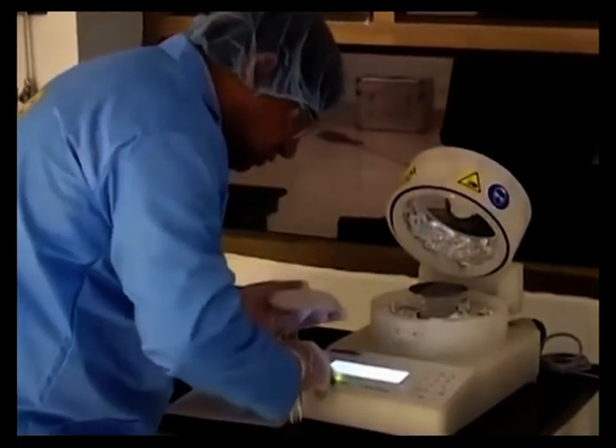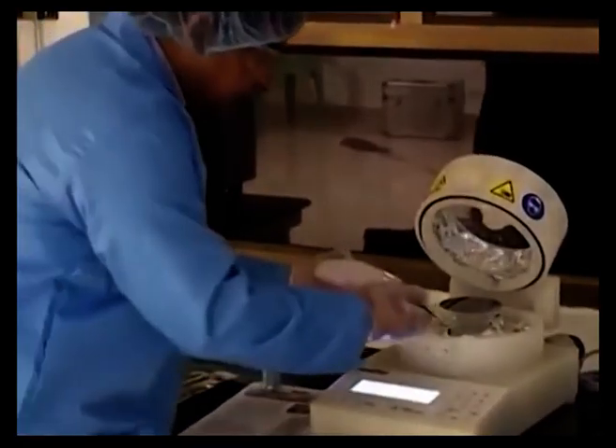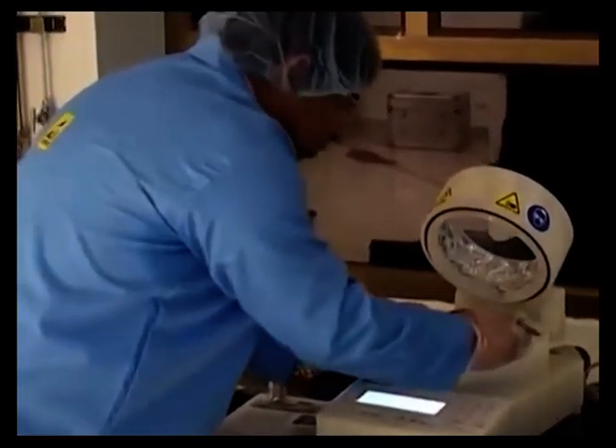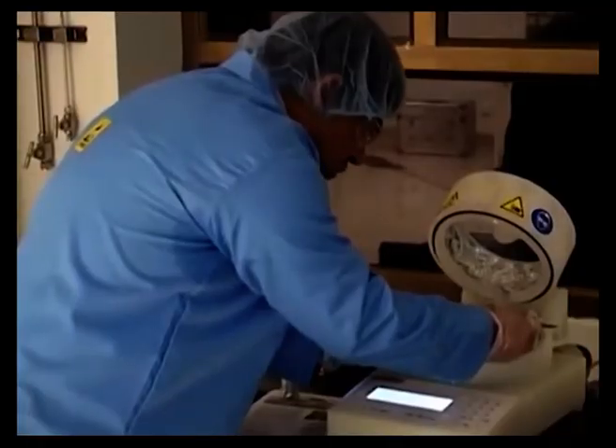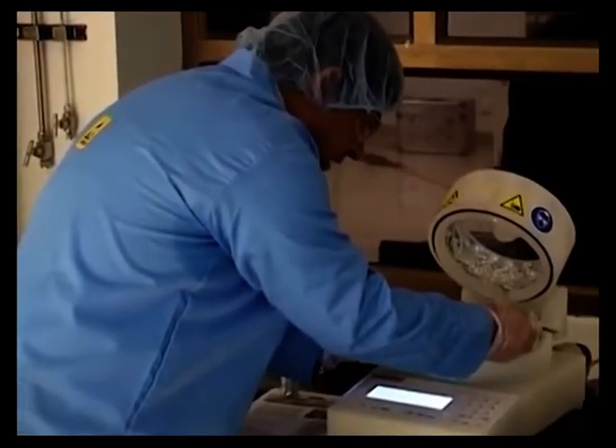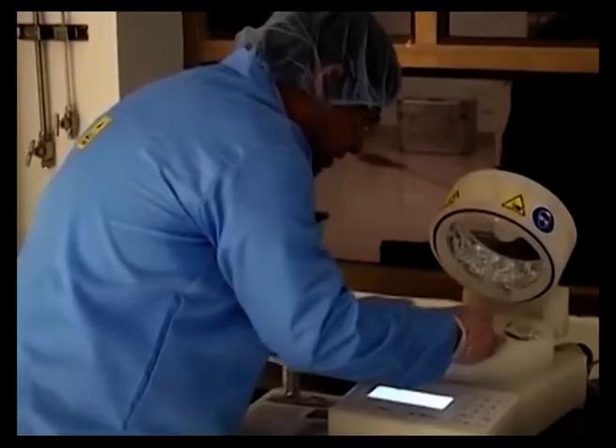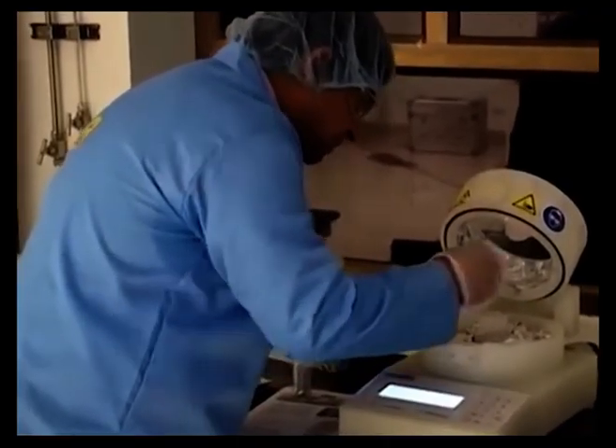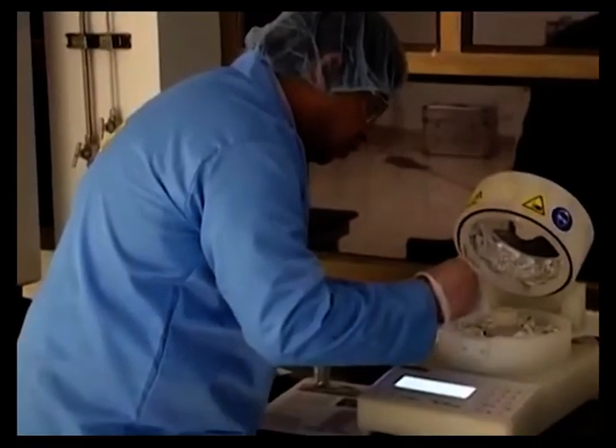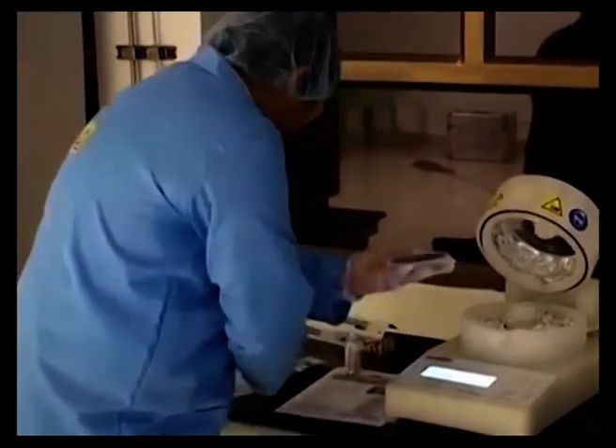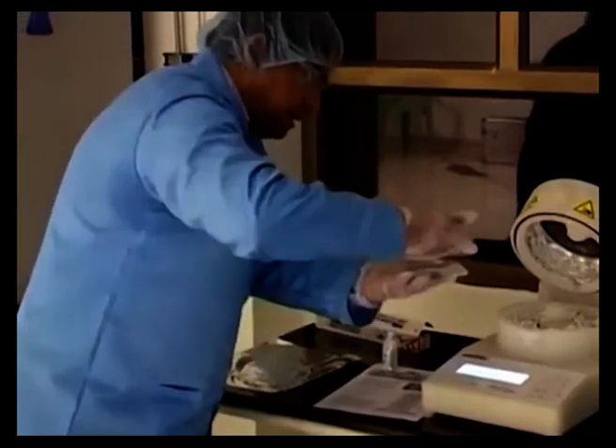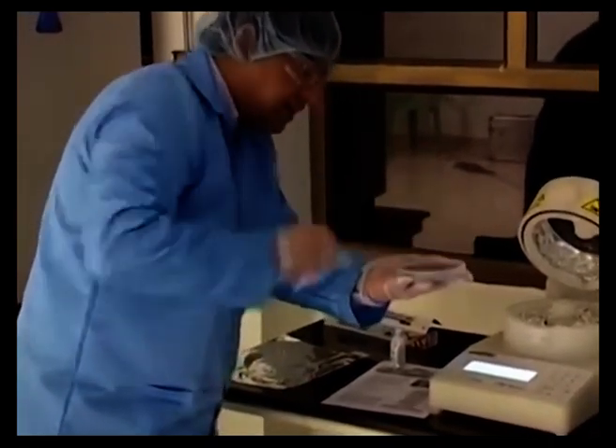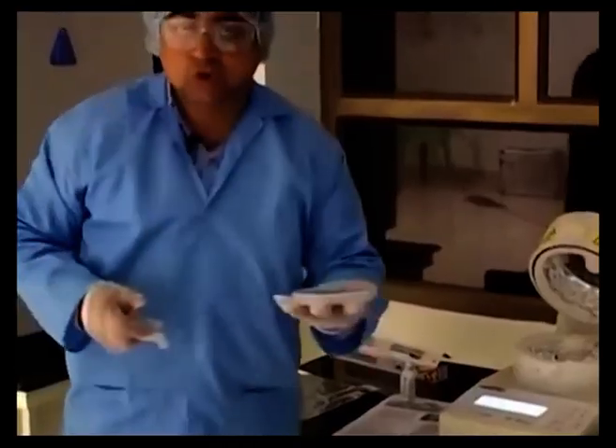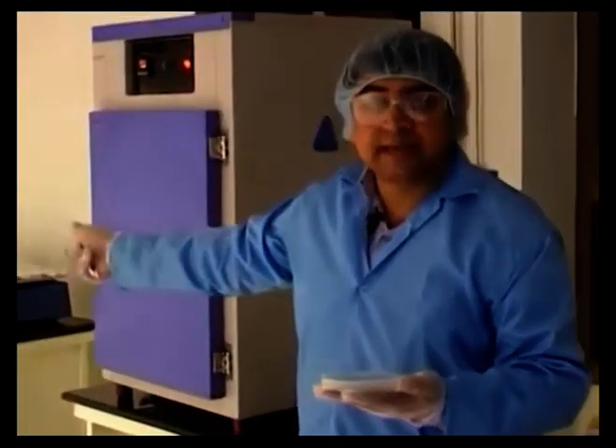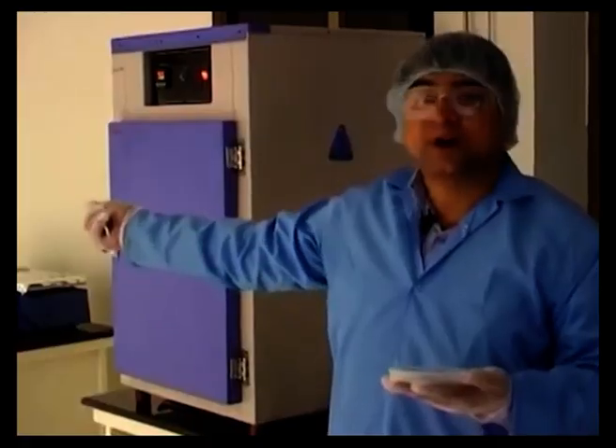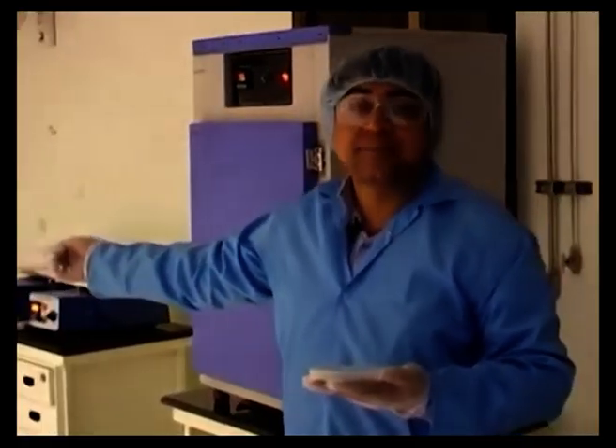So first thing we need to do is to close the vacuum so that we can decouple the wafer from the spin table. We take a very close, very small portion and bite along with this tweezer on that portion, and then slowly transfer the resist coated surface onto this wafer holding box. And then once we have done it, we actually cover it with this cover here, not press it very tightly, and then slowly move towards our next step, which is the hot plate, and keep it on the 65 degree set hot plate and wait there for about 3 minutes or so.